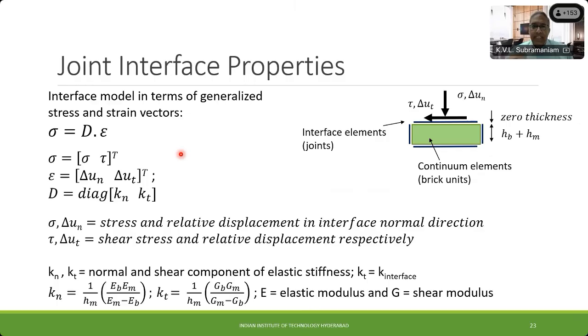So this is a very well-established approach. And then we get into this pseudoplastic kind of a formulation, except now we treat the brick as if it is elastic and perfectly brittle material, which fails by cracking. The interface between the bricks, which used to be the mortar, is now modeled as this infinitesimally thin layer, which has a finite shear versus confining stress kind of a response.